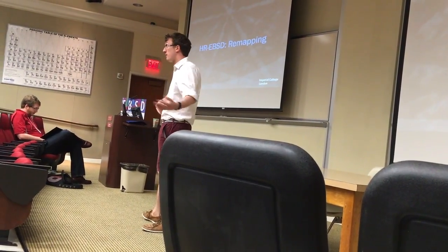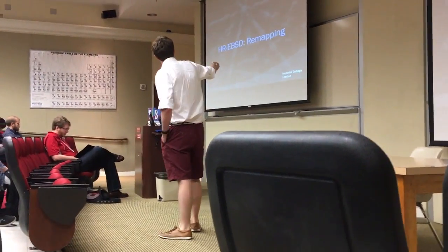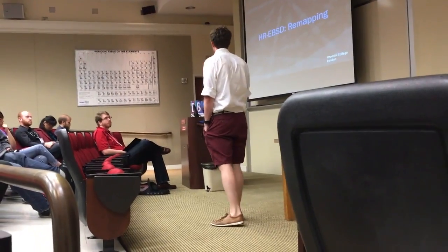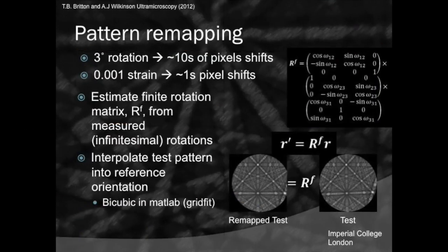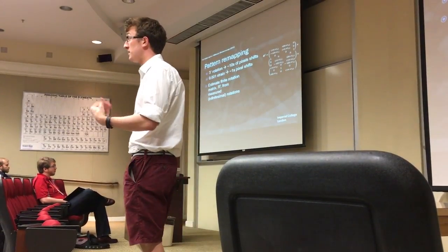Where are things moving forward? We wanted to look at elastic strains in metallic systems, but there was a practical problem: the elastic strain is very small compared to the rotation. The diffraction pattern is a gnomonic projection of diffraction, and as you rotate your crystal the diffraction pattern moves at a different rate depending on where that projection is happening. With large rotations, the pattern doesn't translate simply — we get skew and zoom — and that causes issues.